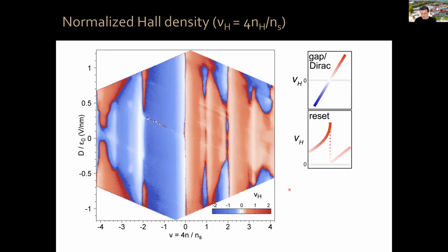And then another feature is associated with Van Hove singularities. At a Van Hove singularity, your Rxy changes sign smoothly through zero, which means 1 over Rxy, or Hall density, diverges and changes sign. So you go from light blue, dark blue, flip sign to dark red, and then light red. This is something that you can see, for example, here or here. You can see this goes from light blue, dark blue, switches abruptly to dark red, and then lighter red. So to zeroth order, most of the features in this phase diagram can be attributed to one of these three situations, not everything, but largely.